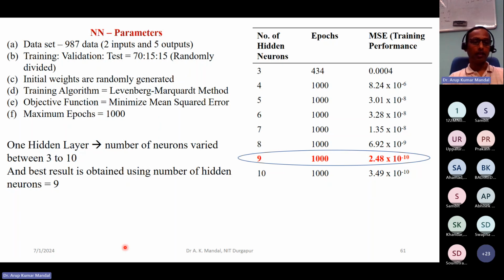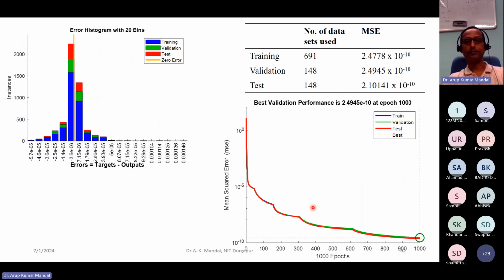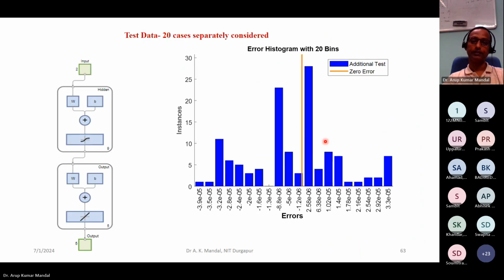And one hidden layer, number of neurons varied from 3 to 10, and we got the best result with 9 hidden neurons. You can see here 2.48 into 10 to the power minus 10 is the best performance in the case of 9 hidden neurons. And here the error histogram, you can see almost perfectly matching. And this is the best validation performance at epoch 1000. This is the error histogram.